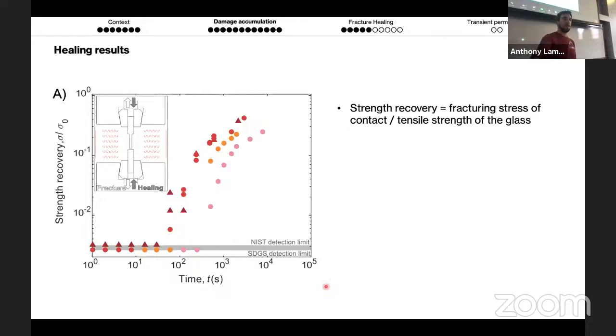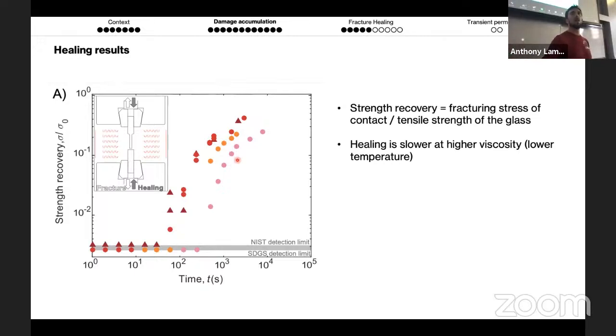What we see is that the strength recovered by the contact is increasing as we increase the time of contact, as you would expect. So more time, you'd have more healing. So here 1 would be fully recovered, and 0 is, it's on a logarithmic scale, basically not recovered. We see that healing is slower at higher viscosity. So higher viscosity is lower temperature. So that's also quite intuitive. If you have a more viscous glass, it's going to take longer for it to recover strength.